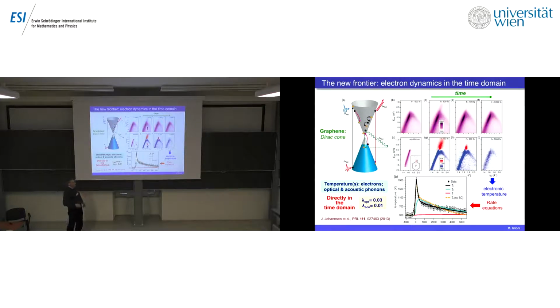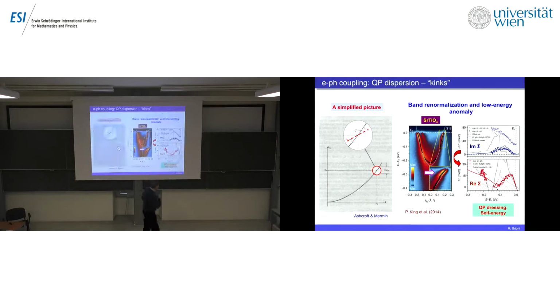From these results, one can deduce the electronic temperature, which is plotted here as a function of the delay between the pump and the probe pulses. And with rate equations, one can model this decay, and from this determine the coupling to the acoustic phonons and to the optical phonons, and these are the values that one deduces, actually fairly small coupling in graphene.